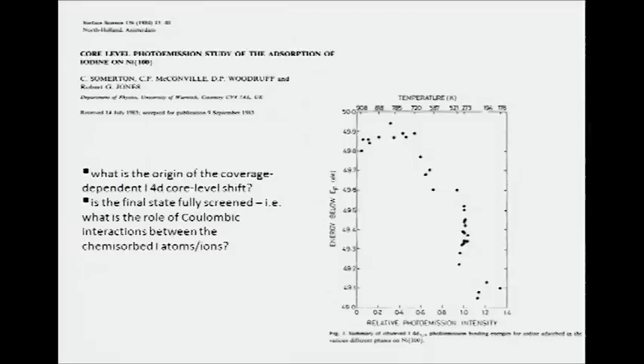So the thing that we were working on at the time when I read this paper and realized it put some nice, simple physical ideas into this, was actually a quite different problem, which was looking at iodine on nickel, and looking at the iodine 4d core level shifts, which, as you see, change with coverage. It turns out that interpreting this is much messier than the system in the Johansson-Martensson paper, because unfortunately the iodine is not in a fully neutral state on the surface. It's partly ionized, and so there are Coulombic interactions between them in the initial state, and also Coulombic interactions in the final state, and then how fully relaxed the final state becomes is important, and it all gets very messy. So in truth, we read the paper, we learned a lot, but ultimately we didn't understand our data, so I'm sorry about that.